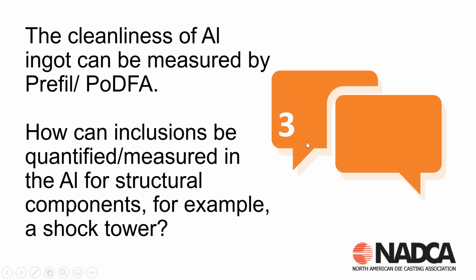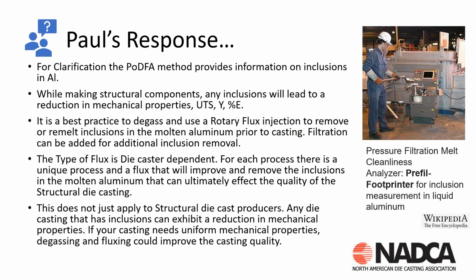This next question has to do with the cleanliness of metal. The question is, the cleanliness of aluminum ingot can be measured by the prefil PoDFA machine. How can inclusions be quantified and measured in aluminum for structural components, for example, on a shock tower? So first off, let's clarify what this means. For clarification, the PoDFA method provides information on inclusions in molten alloys. So we can take molten alloys and check them using this pressure filtration melt cleanliness analyzer, and we can determine the amount and the type of inclusions that are inside our metal. It's typically for molten metal producers.